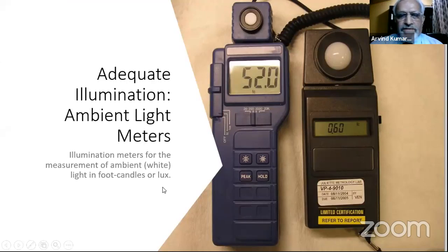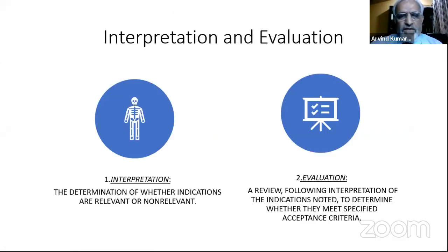So this is the meter which will check the white light intensity. Now the interpretation and evaluation. The interpretation is first you have to see what indications you have got, whether it is a relevant indication or a non-relevant indication. That means really it is coming from a defect or it is coming from the process that you have not carried out properly. It is because of that.